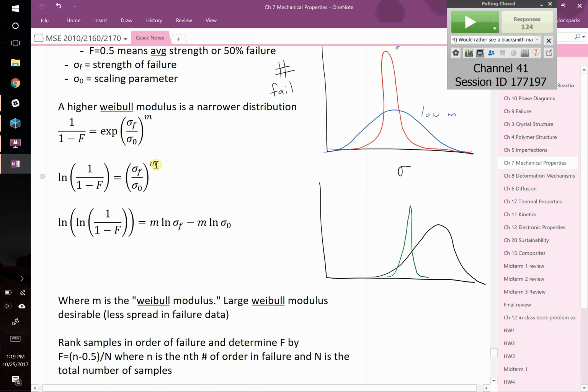Okay, are you getting the same things as me? When I punch these in, I solve for x first, and then if you want to solve for sigma f, you take the exponential of your x value. Therefore, you find that for 1 in 1 million to fail, you can take the stress all the way up to 15.37 megapascals, or whatever the units of stress are here, with the weak material with the tight distribution. But you can only take it up to 5.34 megapascals with the other one.